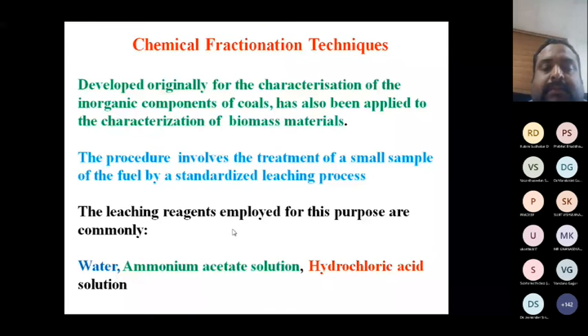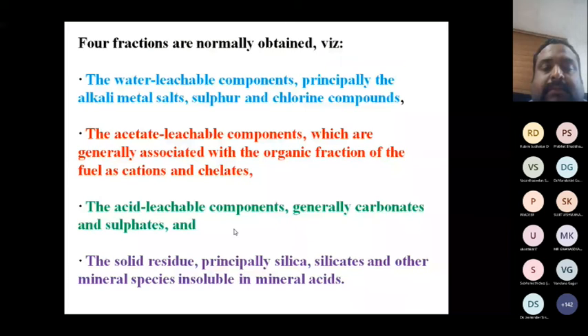Four fractions are normally obtained. One is water leachable compounds, principally alkali metal salts, sulfur and chlorine compounds. The second one is ammonium acetate leachable compounds, which are generally associated with the organic fraction, as cations and chelates. The third one is acid leachable compounds, generally carbonates and sulfates. The last one is the leftover solid residue, mostly silica and silicates. So: water soluble, ammonium acetate leachable, then acid leachable, then leftover residue.